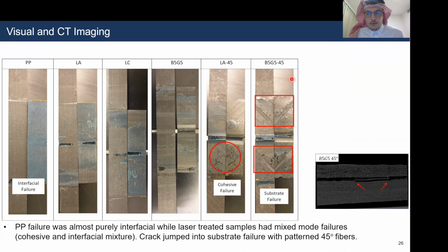For the B5G5 45, that one is the patterning with 45 degrees at the surface, a different failure mechanism happened, which was a substrate failure, such that the crack entered the substrate of the skin and detached fibers of the skin.